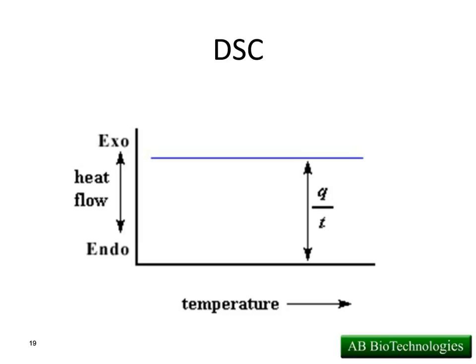So as we freeze down and we warm up, we know the sample is going to go through different transitions, whether it's crystallizing or melting, and it's giving off or absorbing heat. The DSC senses that and says, we're going to pull a little bit of energy away from that to keep the sample pan and the reference pan at the same temperature. So it's the heat flow, the amount of heat over time that's supplied to the sample to keep it at the same temperature as the reference pan.